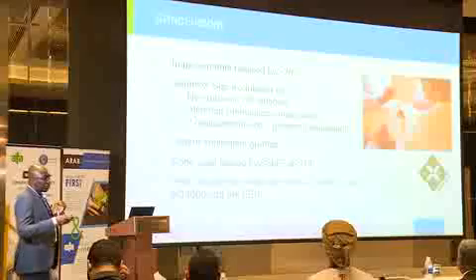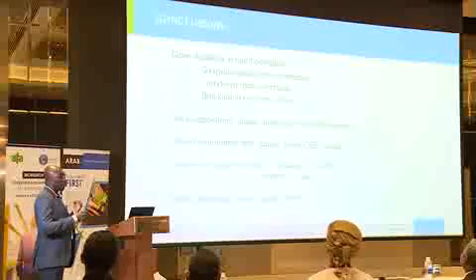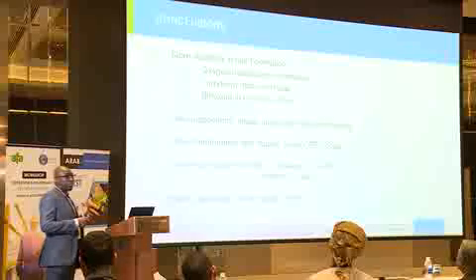So in conclusion, with Safurex Star, we have a material that we believe brings the improvement which I talked about. And finally, when you use Safurex, it gives you more flexibility to operate your plant because the material is much more forgiving. I did not mention it earlier on, but actually in a case, the plant lost oxygen passivation for more than 2 weeks. And they didn't have to shut down.